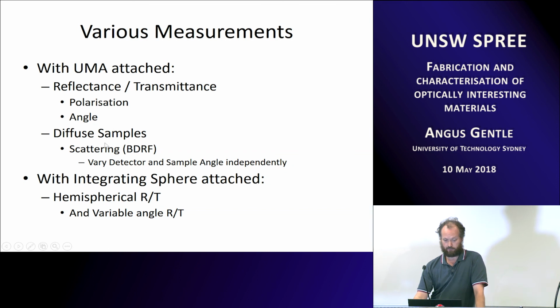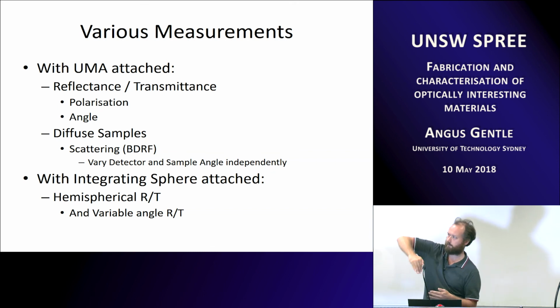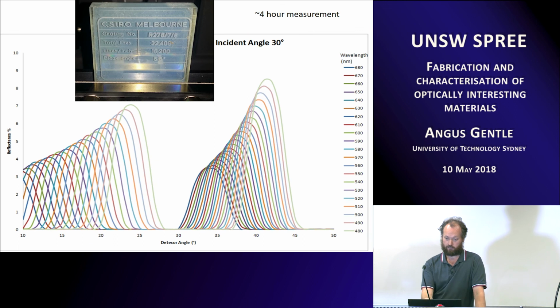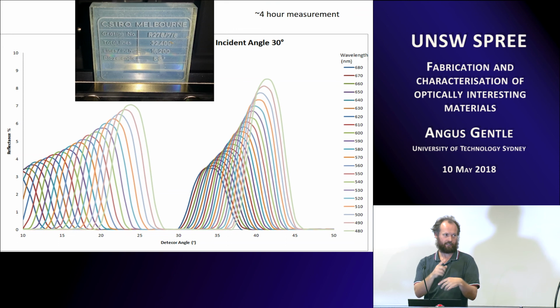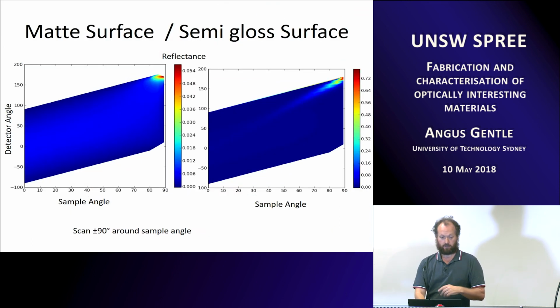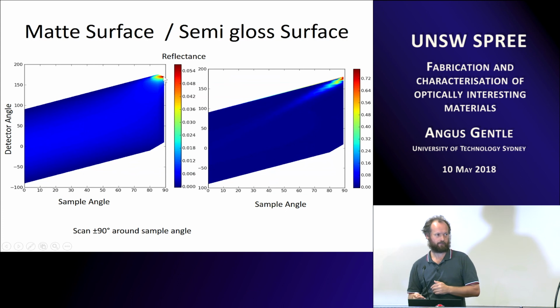So standard reflectance sort of things, plus hemispherical reflectance, R&T, or variable angle hemispherical. So center mount the sample, rotate it around. So this was throwing a diffraction grating on there, scanning across different wavelengths, different angle combinations, so you can see you get quite nice data out. This is scattering, taking a matte paint and a semi-gloss paint, and so you can see the matte paints are actually quite good up until the very highest angle there, where it's actually missing the very end of the sample because you've only got so long you can go.